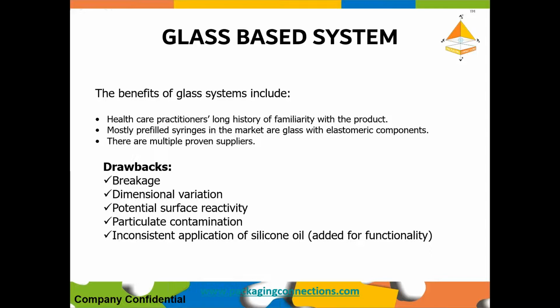The drawbacks which we see now with glass-based syringes are breakage, though it is much more controlled now with handling and everything, but glass itself is prone to breakage. Anything with glass always has breakage seen as a drawback. Glass dimensional variation is higher than plastics. There is potential surface reactivity, and stability could be a concern in some cases. We need to do more work for decontaminating them. And to make the movement of the plunger inside smooth, silicone oil is applied, and consistent application of silicone oil is always a challenge, so there could be inconsistency.